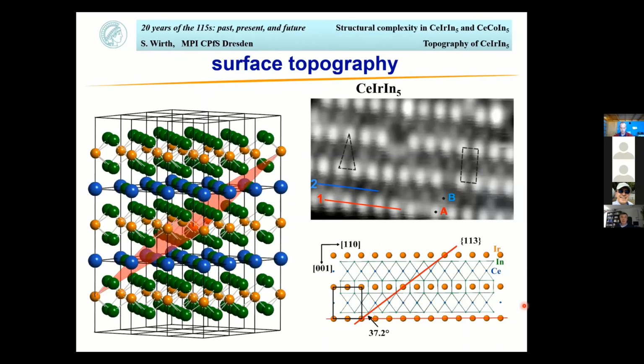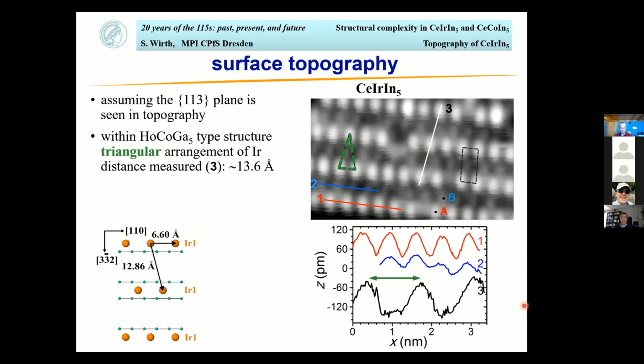How does it help? So it's a pretty strange plane here in the crystal structure. But now with this, we can actually get to the bottom of these different arrangements. If I now take a line scan along this line, which corresponds to the triangular arrangement, look here. So we actually see distances which are 13.6 angstrom apart. So this corresponds to a distance between the iridium of 12.9. This is now the 113 plane of the holmium cobalt gallium 5 structure, and you expect this triangular arrangement.